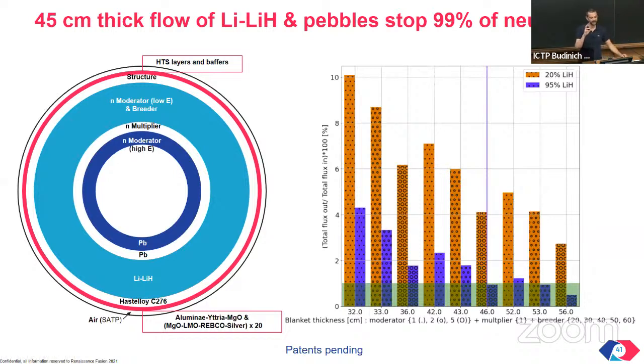And this is important because some of the neutrons will escape from the reactor. But if we really want to make a closed loop, where for each reaction in the plasma, we produce a triton, which is reinjected in the plasma, we need to compensate for these neutron losses. So you need a neutron multiplier. The lead does just that. And this layer of materials protects, back to your question, sir, protects the superconductor from damage by neutrons, from nuclear heating, etc.